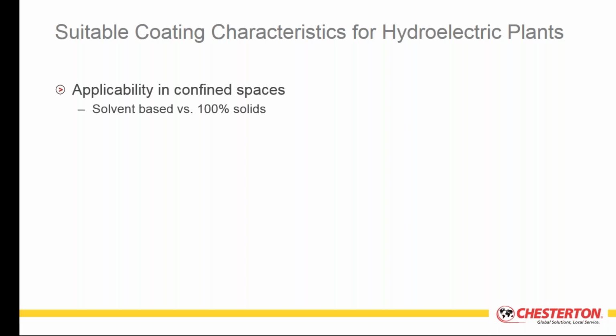This is a great concern, particularly based on the accident that occurred at Xcel Energy about 6 or 7 years ago out in Colorado. In that instance, several workers were killed in a fire that occurred in a penstock. The fire occurred when a flammable solvent was ignited inside the penstock. The workers downstream of the fire were able to be evacuated, but the workers upstream had nowhere to go, so they moved upstream from the fire to the point where they could no longer climb up the incline. That's where rescuers eventually found them in the recovery process.